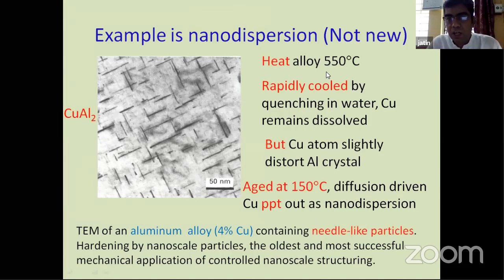But now if you heat this alloy at 550 degrees Celsius and rapidly cool it, your copper remains dissolved. But the copper atoms slightly distort the aluminum crystals. They start precipitating out. If you give a little energy for the copper to precipitate out, they will take the shape of this. It is called the CuAl2 phase. So they take the shape of some needle-like particle. You can see with the help of this nanometer marker what this needle-like particle is.